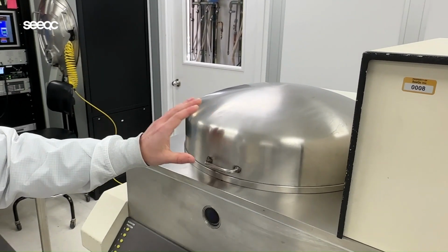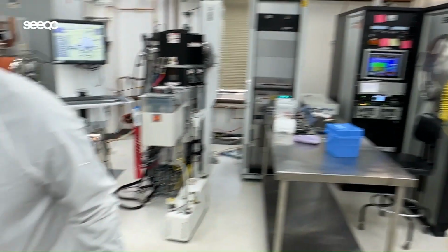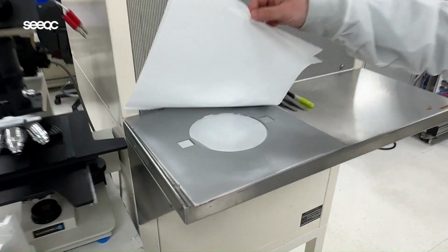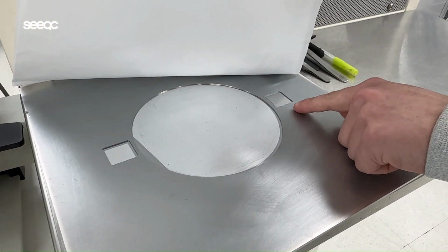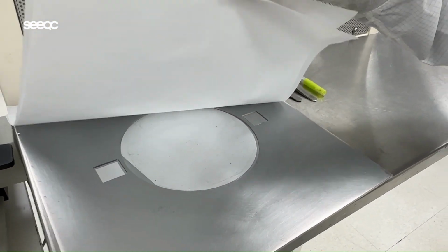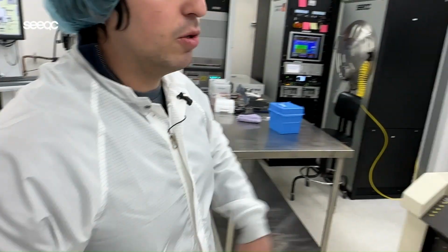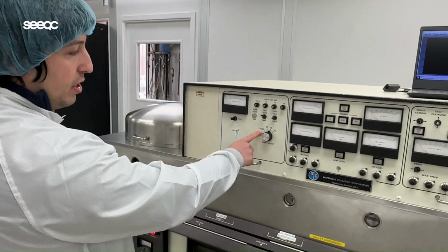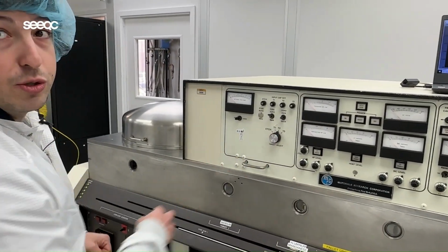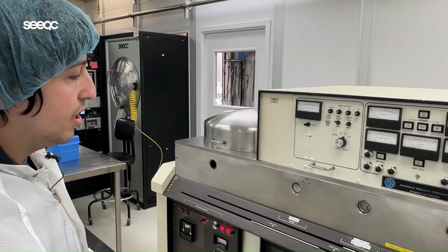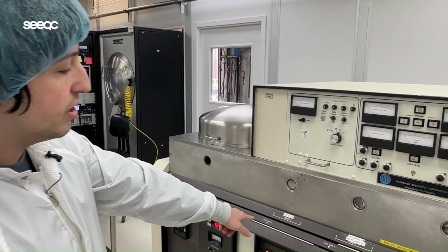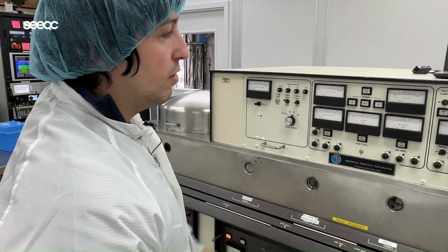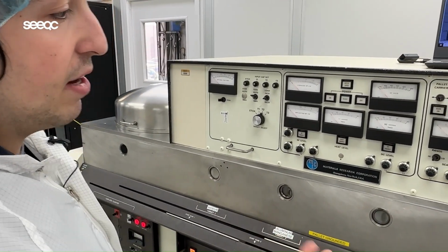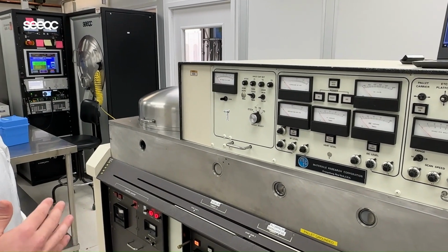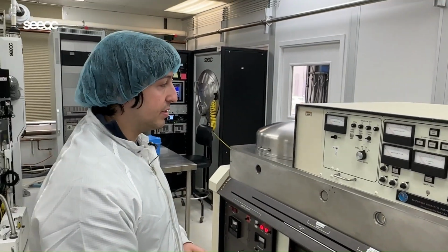So in here, you can load wafers onto a pallet that looks like this. And we can put glass slides to use for our measurements on the other tools that we have. After it goes in there, we can do a little bit of an argon sputter etch to clean off the wafer of any oxides. Then we can choose which one of the metals we want to deposit for a certain amount of time, and that will determine the thickness of the niobium deposited.